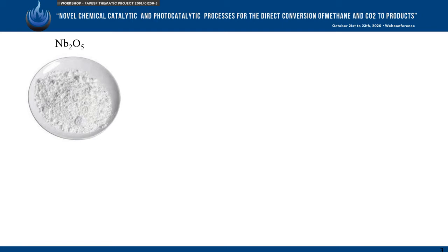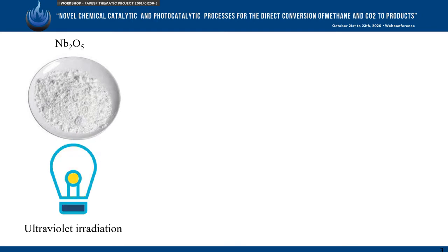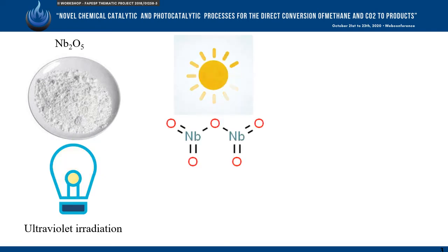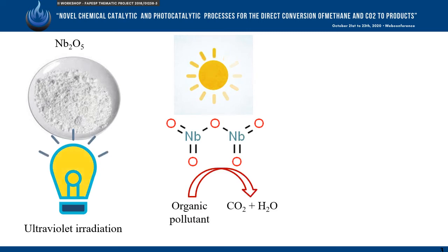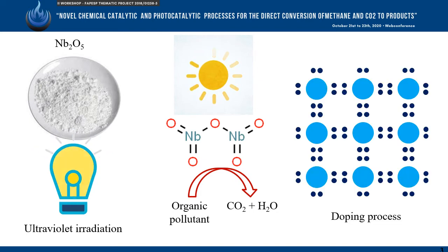Photocatalysts are materials that need illumination to be activated for decomposing organic pollutants. Niobium pentoxide is one of the most applied photocatalysts, and it is activated only under ultraviolet radiation. However, it is interesting to activate niobium pentoxide under visible light, since it would be possible to use sunlight to drive the desired reactions. This modification can be accomplished by the doping process, in which some matrix atoms are substituted by a foreign element.